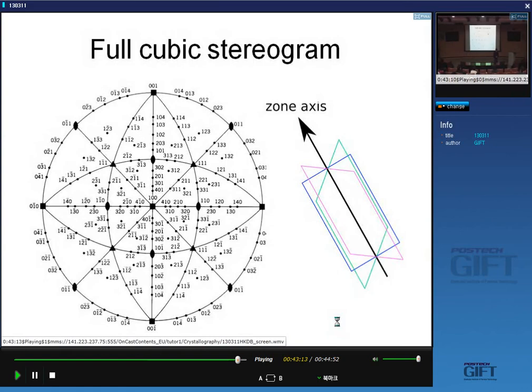So from the stereogram, you could easily draw electron diffraction patterns. All you have to do is identify two planes, okay, which spots correspond to those two planes. Everything else is generated by linear combination of those two. I'll show you this later on in the lectures. So once you have a stereogram, your electron diffraction patterns are almost defined. You have to take account of structure factors. Structure factors are things which lead to systematic absences, which we'll come to later.